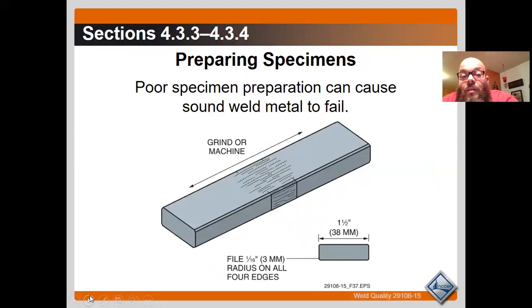Preparing specimens. Poor specimen preparation can cause sound weld metal to fail. Okay, it's important that everything's ground smooth and the edges are slightly rounded. And we don't want to take off too much material. If you're turning in a 1-inch plate to weld and you have an inclusion you're trying to grind out and your weld area that I'm going to bend is only 5/8 of an inch thick, it's going to fail.